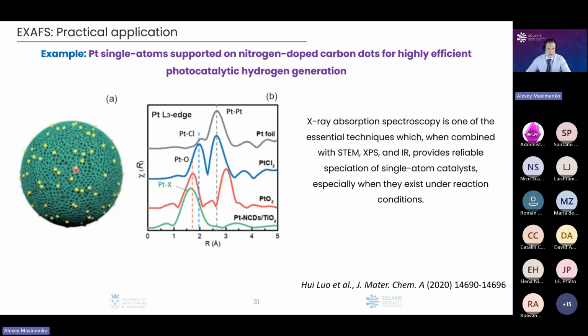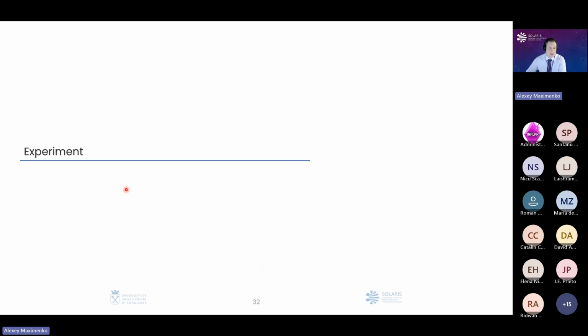So that is why it is said that using X-ray absorption spectroscopy, and mainly the EXAFS region, you could prove that the catalyst which you make is not small clusters or small nanoparticles, but is actually the single atom catalysis which you are interested in. That's what kind of information we could get from the spectra, and some examples I showed you.